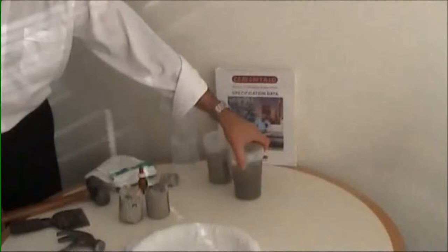But this is a situation I'd like to explain to you, because the two concretes we're going to look at now are both so-called integral waterproofers. Both of them had a 30-minute water absorption, when tested at 28 days, of around 1%, or just under 1%. We thought it would be interesting to not run the sample underwater for 30 minutes. I mean, that really doesn't tell you too much about the life of the concrete, how it's going to perform in the structure. We thought it might be fun not to leave it in there for 30 minutes, maybe 3 hours or 3 days. Well, hang on, let's leave it underwater for 7 days and actually see what happens.